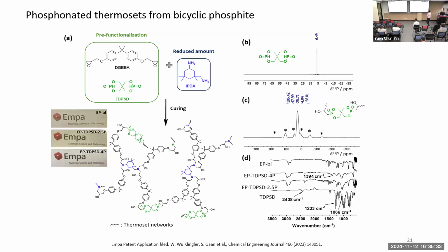Don't want to go into details. How do we make this? So to do this, you need a special monomer. In our case, we have this cyclic phosphoester monomer on the top, you can see on the left. And it's actually a reactive monomer which reacts with the epoxy resin. And then it is hardened with an amine. So you need all these 3 components to make a network which is dynamic in nature. And the dynamic bond is this green part where phosphorus is connected to a carbon and it's connected to 2 oxygen at the same time. And the material is transparent in nature.